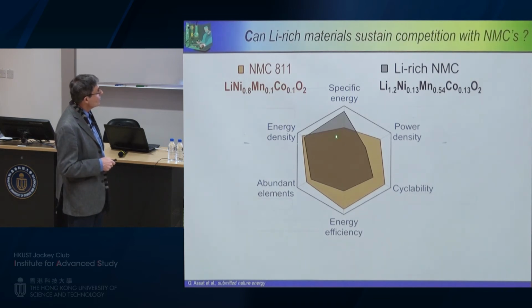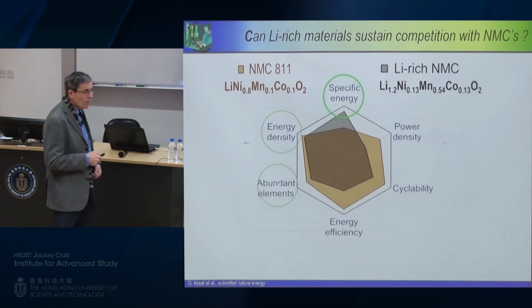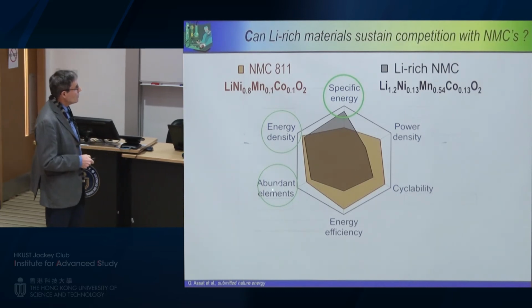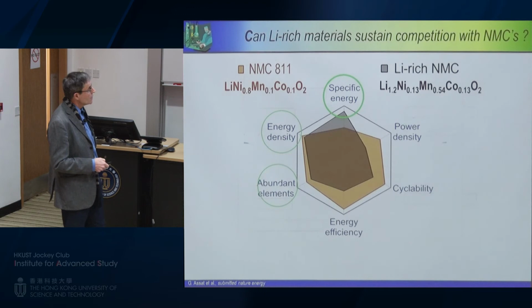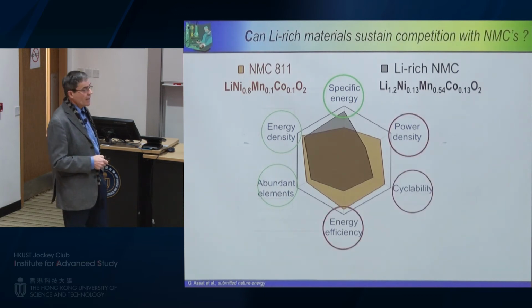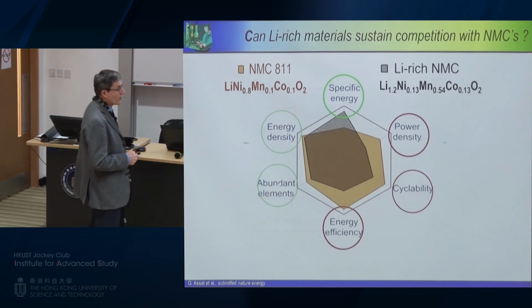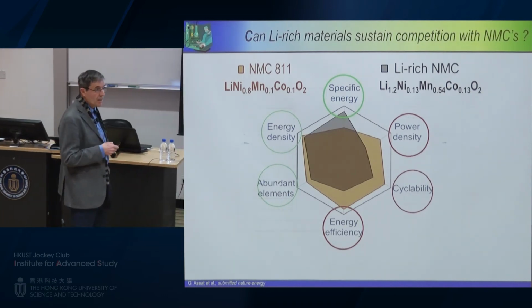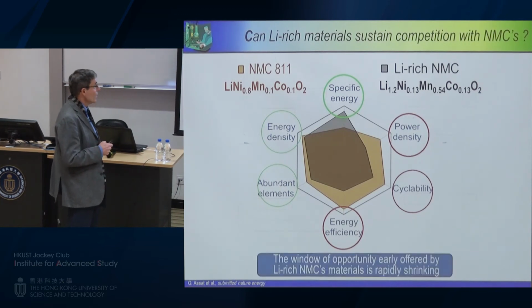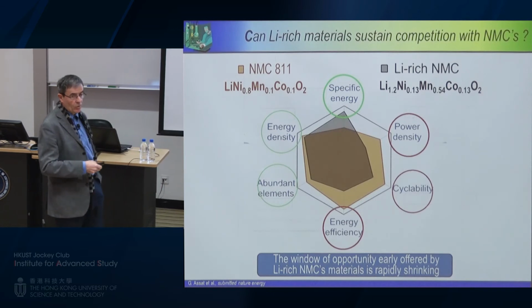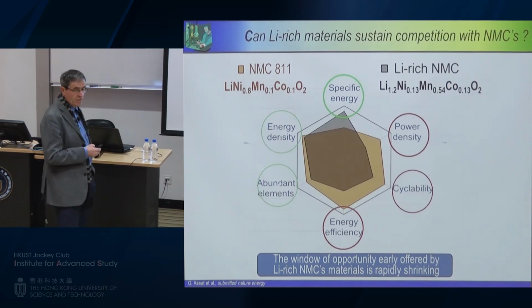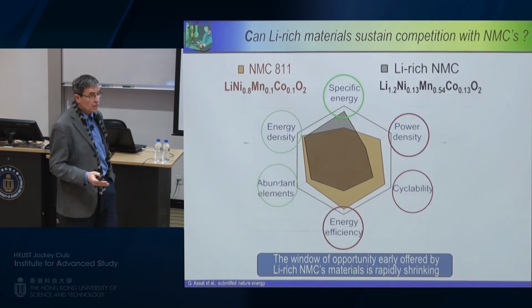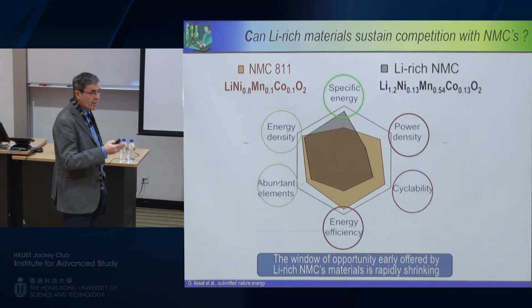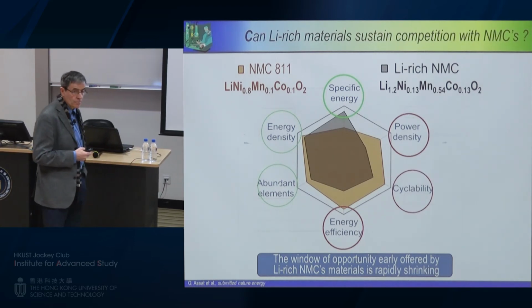You can see now this lithium-rich NMC presents some advantage in terms of specific energy. They are relatively similar in terms of energy density, in terms of abundance of elements, more or less the same. But look, in terms of cyclability and power density and energy efficiency, the lithium-rich NMC cannot compete with the NMC 811. So, bottom line, the window of opportunity that these materials were offering 5 to 10 years ago is closing very rapidly, and will even disappear if we don't succeed in finding a solution to this kind of voltage fade and hysteresis that I mentioned to you.